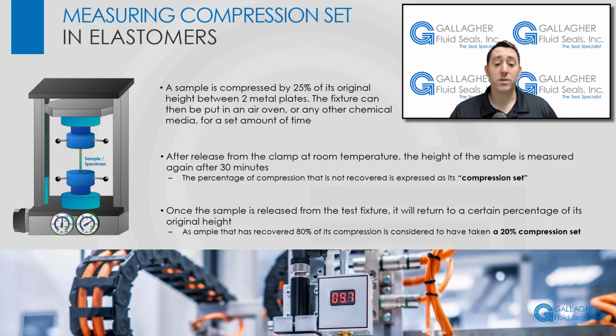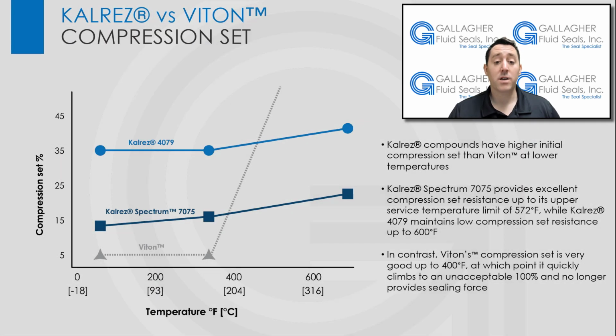Once the sample is released from the test fixture, it will return to a certain percentage of its original height. For example, a sample that has recovered 80% of its compression is considered to have taken 20% compression set. Kalrez compounds have higher initial compression set than Viton at lower temperatures.